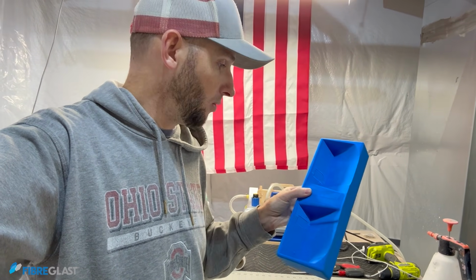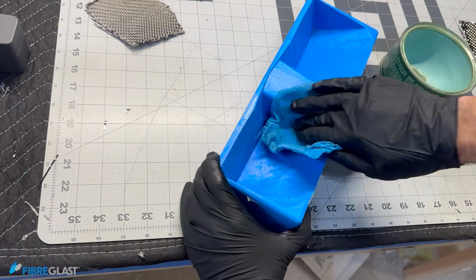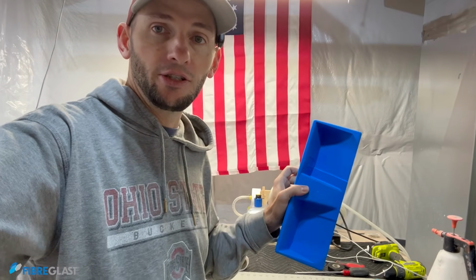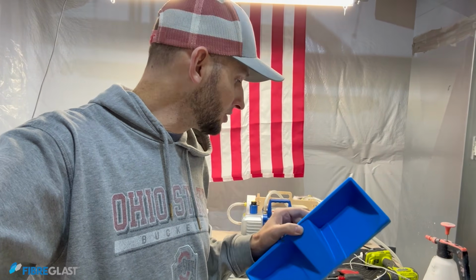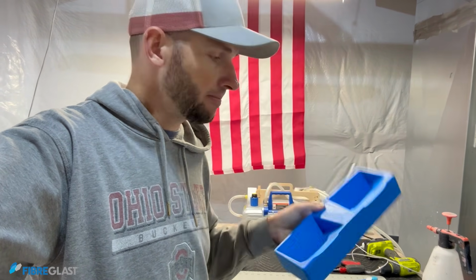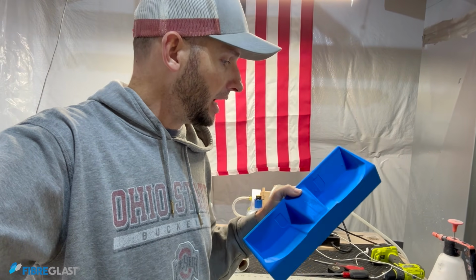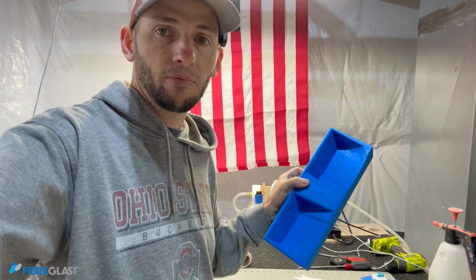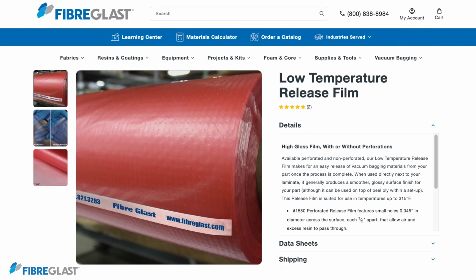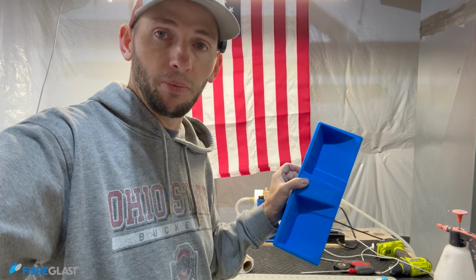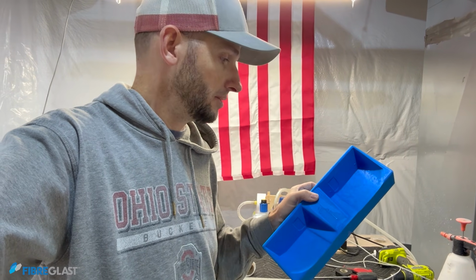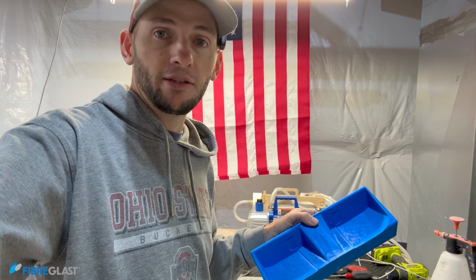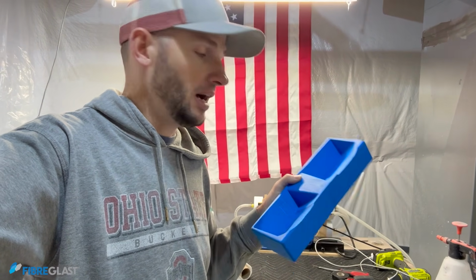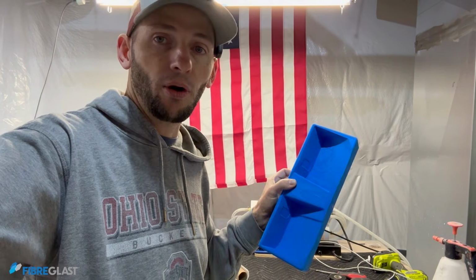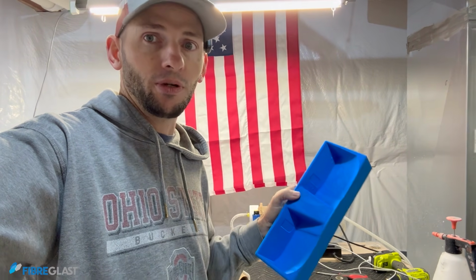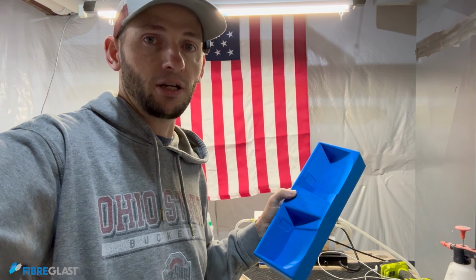I am, though, from what I learned last time, going to use Partall paste for my mold release. I want it to come out of this a little bit easier, and I'm hoping that will help me do that. Everything else about this layup will go basically exactly the same, with one more exception. Typically, you would use what's called release film on a hand wet layup like this that would go between your peel ply and your breather. That release film is a film that doesn't stick to the resin, but it has some very small holes in it that limits the flow of the resin from the carbon part into the breather, which, as you remember, was my main issue. The breather sucked up all that resin.